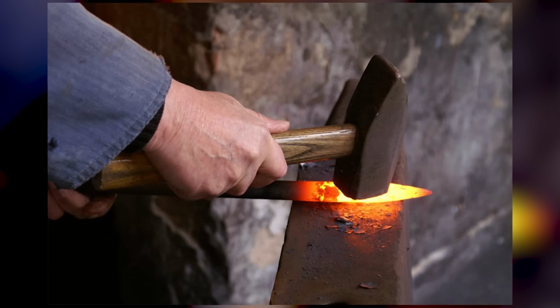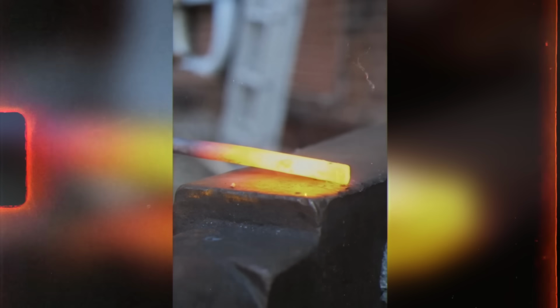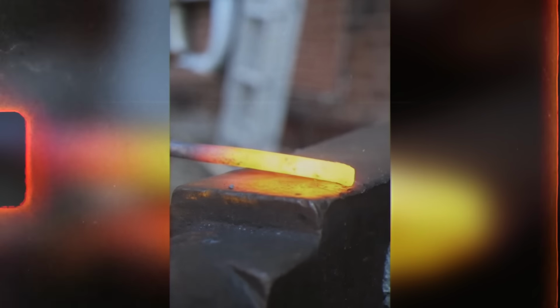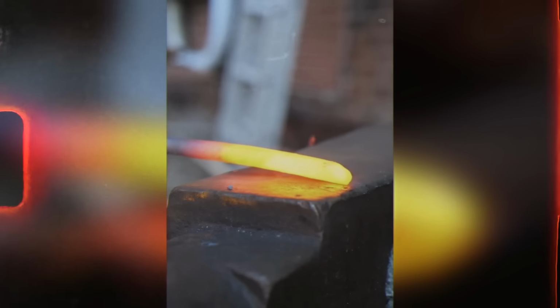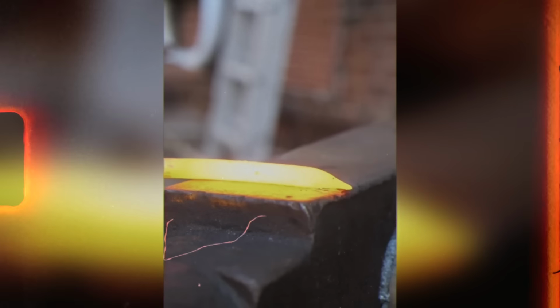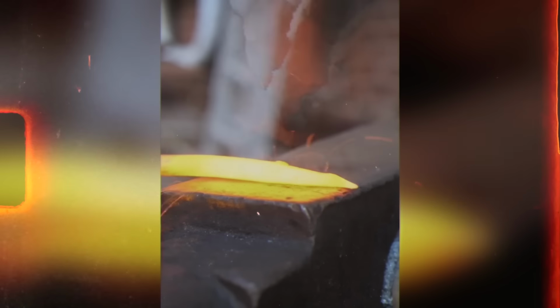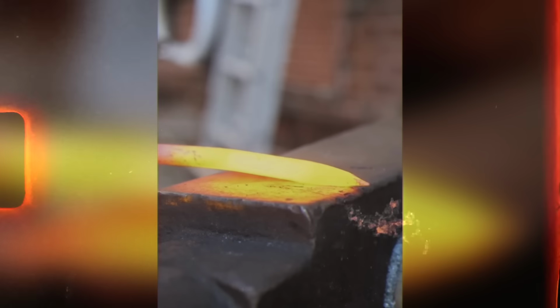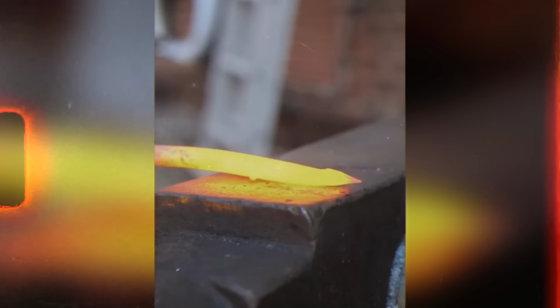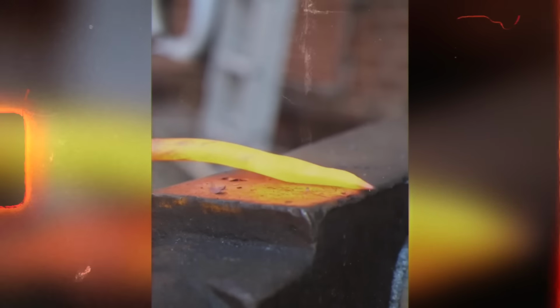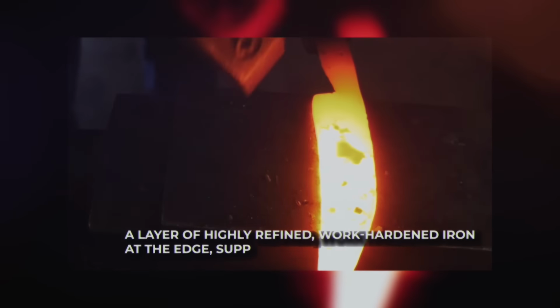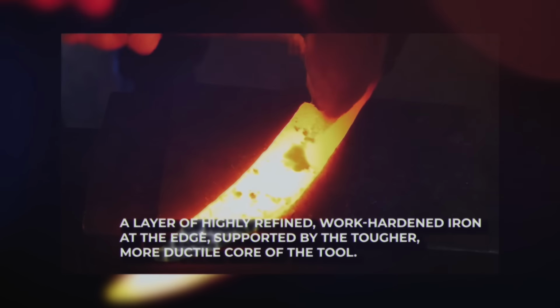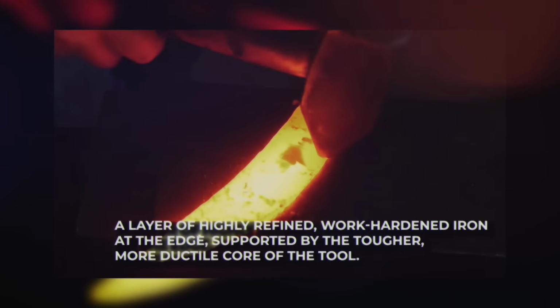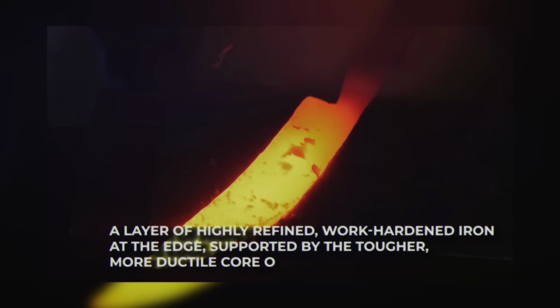What was happening? Each light strike compressed the surface layers without significantly heating them. The metal near the edge was work-hardened through mechanical deformation, but because the bulk of the tool remained at forging temperature, the edge could not crack. The mass of the tool acted as a heat sink, preventing the edge from cooling too rapidly. The result was a compression zone, a layer of highly refined, work-hardened iron at the edge, supported by the tougher, more ductile core of the tool.